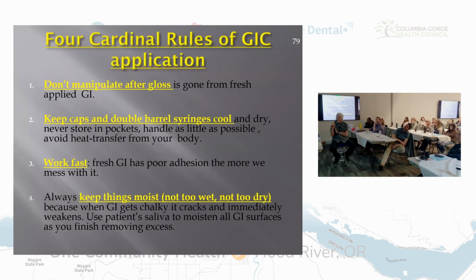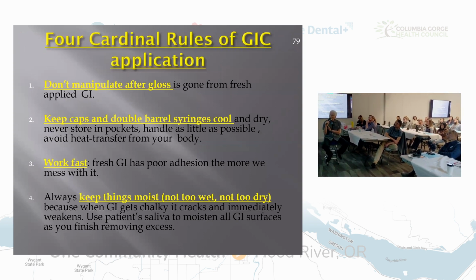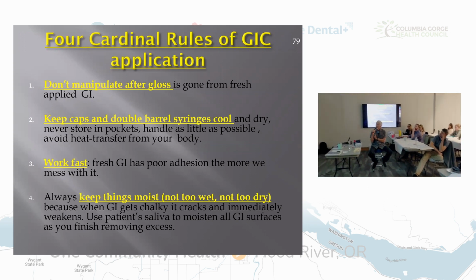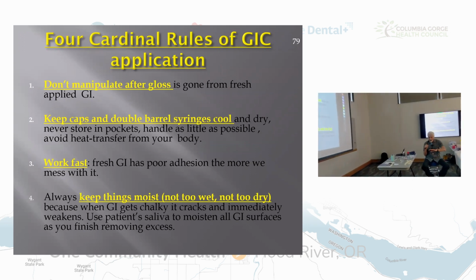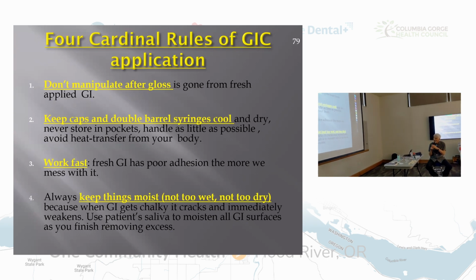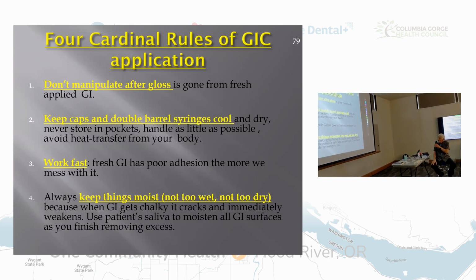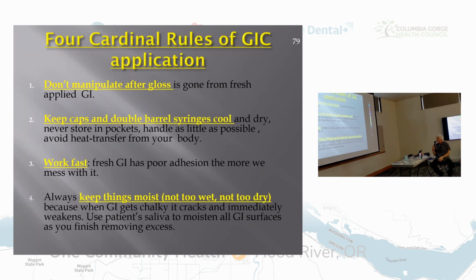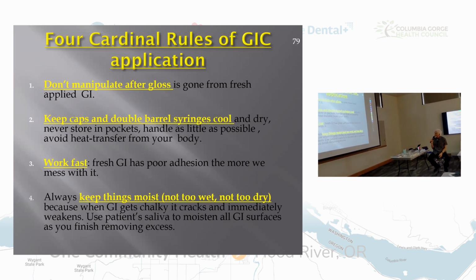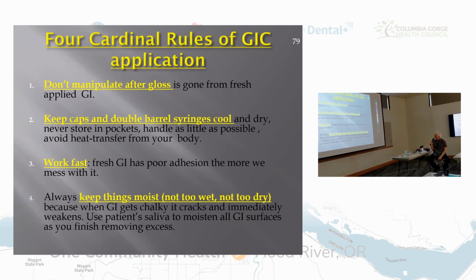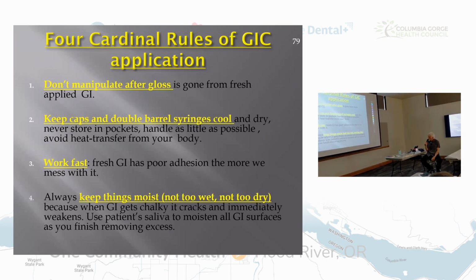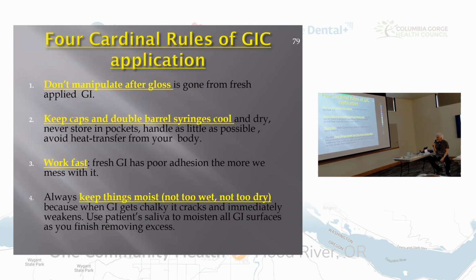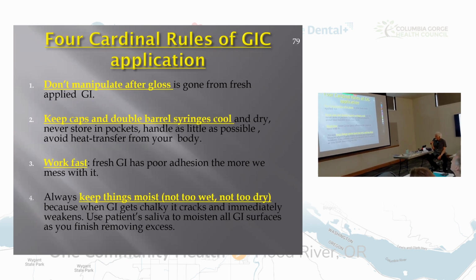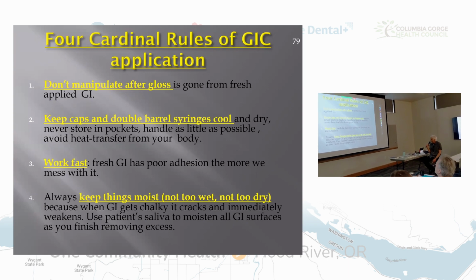Okay, 4 cardinal rules. Don't over-manipulate after gloss. After it's glossy, it's gone. After the gloss is gone from fresh glass ionomer, you're done. Keep the capsules and double barrel syringes cool and dry. Never store them in your pockets. Don't handle them. Don't keep them in your hand. Handle them as little as possible. Avoid heat transfer from your body. And work very fast. Fresh glass ionomer has poor adhesion the more we mess with it.